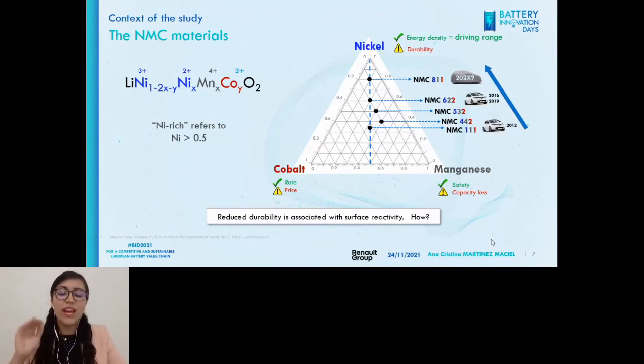...you will see that the trend for the last years has been to increase the amount of nickel. This is because the nickel content is the one that will increase the energy density, and as a consequence the driving range. If you see this phase diagram, you will see that we want to get away from a high amount of cobalt because of its price and its concerns due to extraction. And also, we want to have a low amount of manganese because we have capacity loss, just because the redox couple is not active in the potential range.